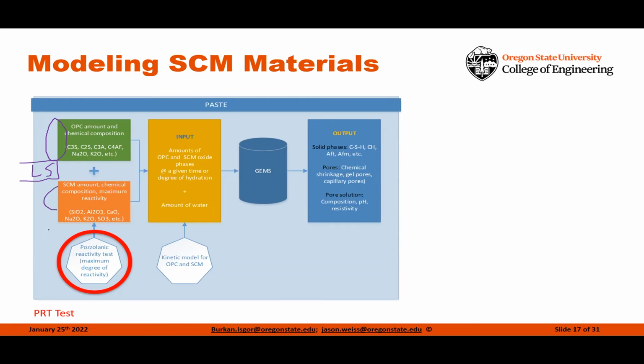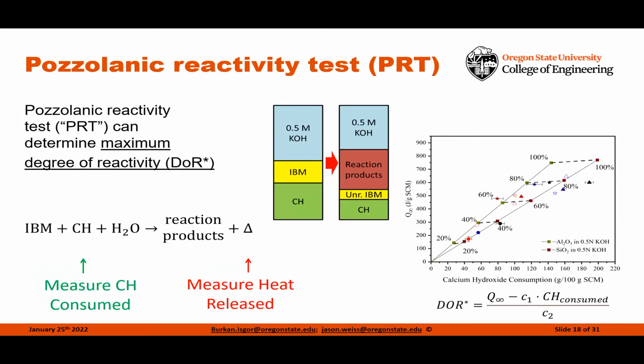This could be fly ash, this could be slag, this could be ground up shells, this could be all sorts of other materials. And as long as we know the chemical composition of the SCM, and how much of that material is going to react, this simulation can be performed. So what we're actually doing is performing a very rapid test where we can measure the heat release and the calcium hydroxide consumed and determine how much of this system is available to react.